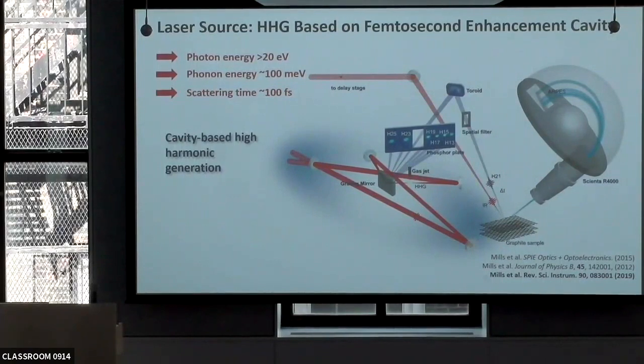However, when this is done with a single pass, so a single pulse going through a gas jet, you really have to amplify your pulses so much that you lose the proper relation between the temporal characteristic of your spectrum and the energy characteristics of the bandwidth. So effectively, you can generate up to X-rays with very high temporal resolution and extremely poor energy resolution. Extremely poor means you wouldn't be able to look at anything like that.